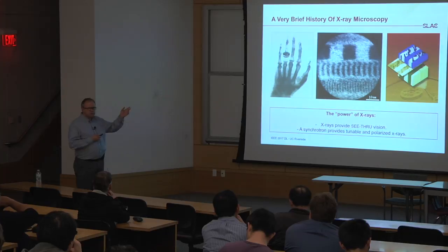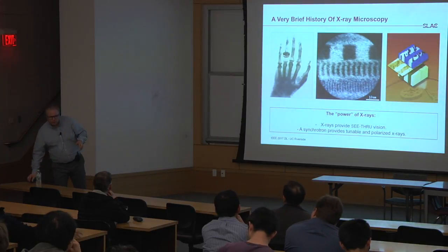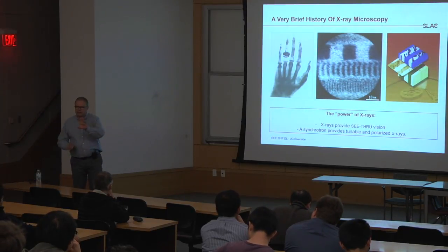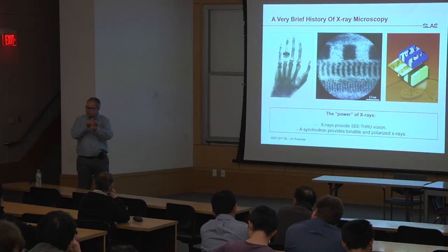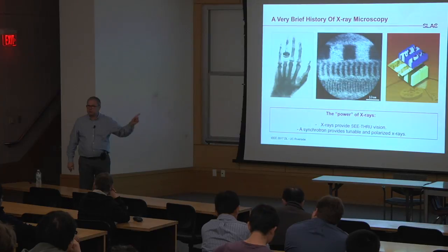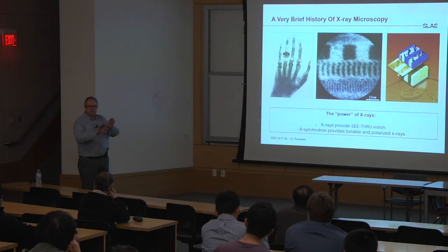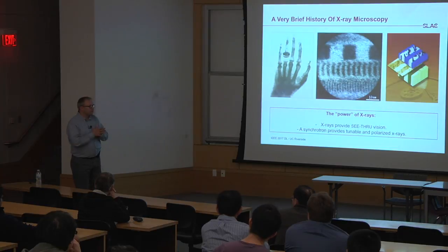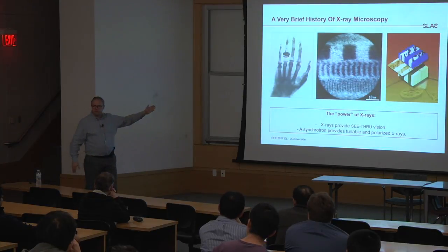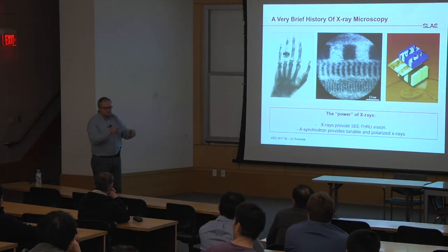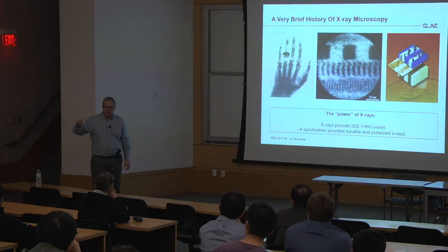The question at this point is really, it becomes an intensity question. Even if you can see a 10 nanometer domain, that doesn't mean that you can get a spectrum from that 10 nanometer domain. If you do X-ray microscopy, you will learn over the years that your eyes are incredibly sensitive. Your eyes can see domains that no filtering algorithm can ever see or detect. We have done microscopy very often on this. We look at the screen and say, there are the domains. And then you put a line scan through it, and that line scan is just noise.